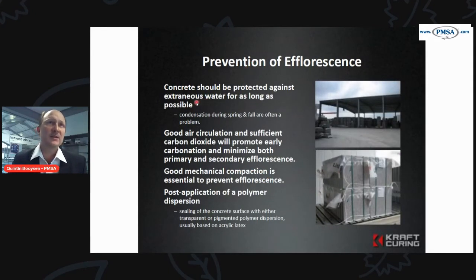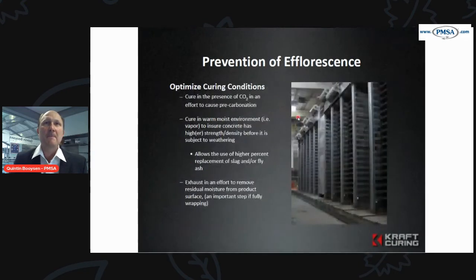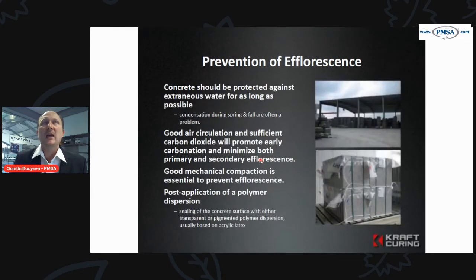Prevention of efflorescence, other methods. Concrete should be protected against external water as long as possible. Good air circulation, allowing sufficient carbon dioxide, will promote early carbonation and minimize both primary and secondary efflorescence. So in a good curing system, as in the previous photo, we actually saw there a curing room. We're able to put in proper circulation systems that will allow equal curing throughout the room, equal temperature, equal distribution of heat, equal distribution of moisture, so you get a more even curing process going on.